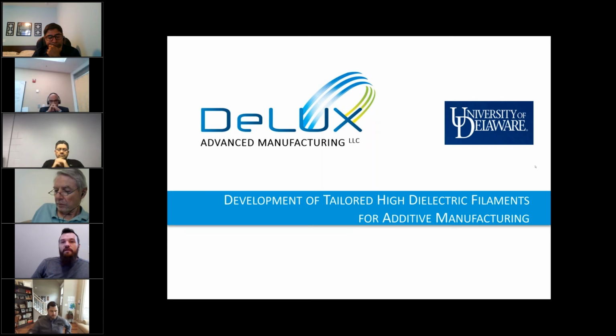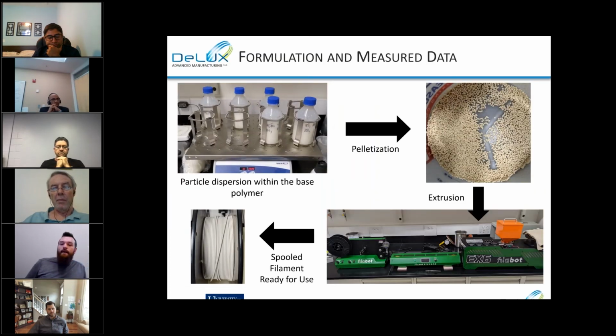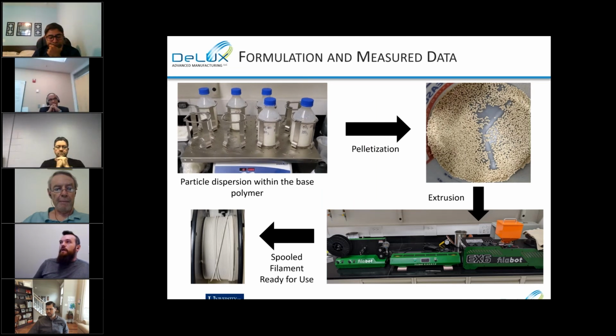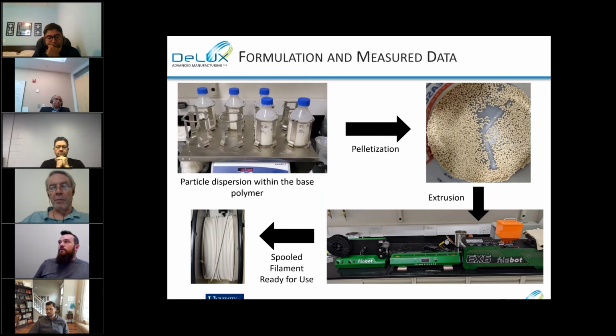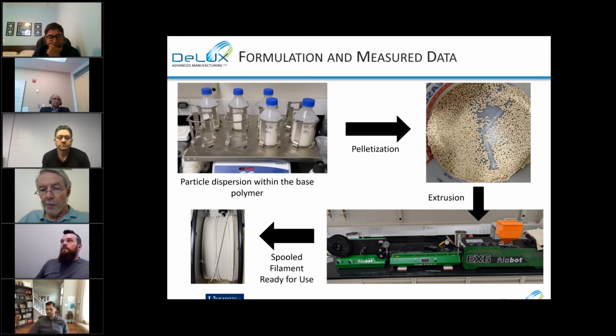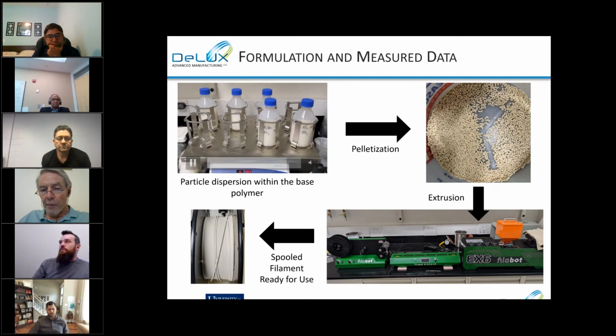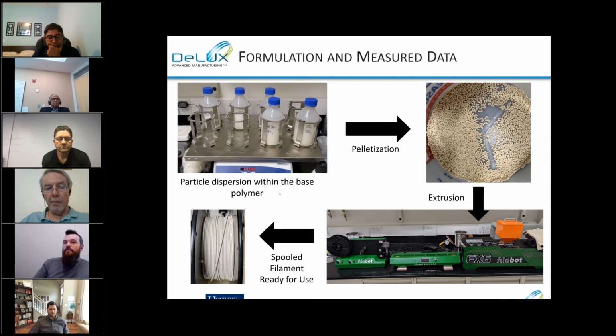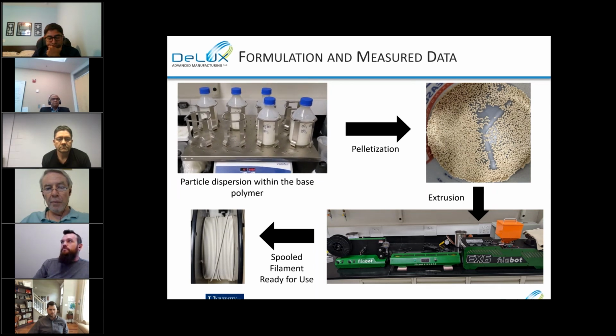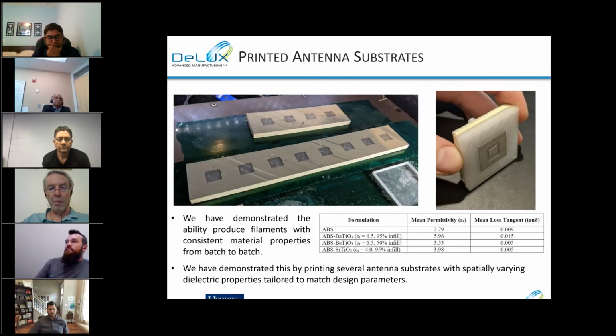So the next thing I want to talk about is development of tailorable dielectric feedstock for additive manufacturing. Again, it was mentioned earlier, but tailored dielectrics allow you to do some really unique and interesting RF devices and structures. In this slide here, I'm showing just generally our process for producing tailored dielectric filaments. We disperse dielectric particles within our base polymer. We pelletize those, run an extrusion, and create spools of filament. And so for something like this dual nested patch antenna, to get the performance that we need, we're actually using 3 different dielectric constants all in one single substrate.